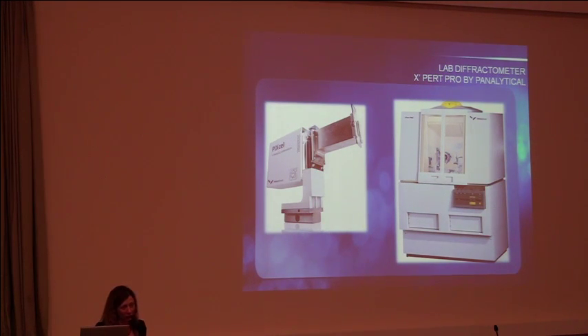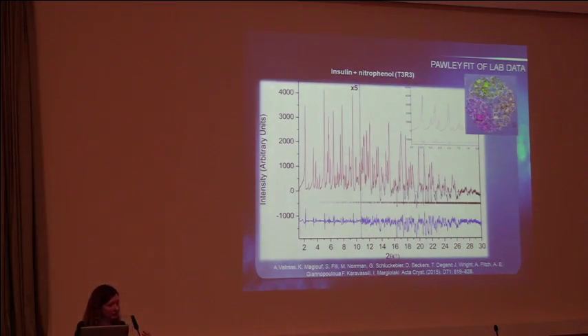In 2013, we installed this laboratory diffractometer from PANalytical in our lab in Patras, which has a parallel beam, focusing beam geometry because it has mirrors focusing the beam on the detector surface. The detector is a very high-tech detector based on the Medipix project, basically the project which resulted in the Pilatus detector. It's a very low background, highly efficient detector, and we routinely collect data which look like this. This is an insulin sample complexed with a ligand called nitrophenol, and it's a hexameric form of insulin.